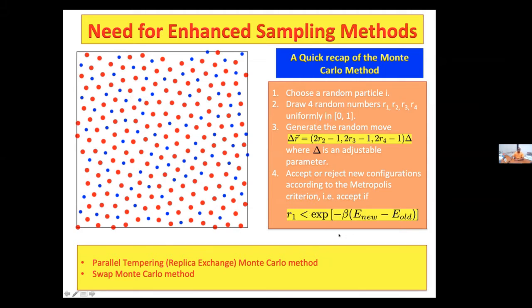But the problem is that using this method, you can only access a reasonable degree of supercooling in a model glass forming liquid. And you cannot access the deep glassy phase because the equilibration time becomes extremely large. For example, to give you an idea, if you take a typical system of a few thousand particles and do these Monte Carlo simulations of a glass forming liquid, then to get a relaxation time of order 10 to the 4 or 5 picoseconds, you really need to run your computer for roughly 2 weeks in real time. So now you can imagine, gaining another decade of relaxation time, you have to run for 20 weeks, which is nearly impossible with the current computational abilities. So this is where enhanced sampling methods are essential, and this is exactly what I'm going to talk about.